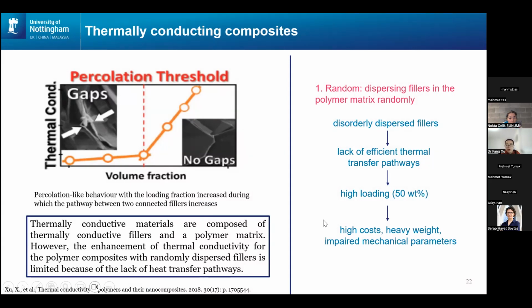So those disorderly dispersed fillers, or randomly dispersed fillers, don't have an efficient thermal transfer pathway. We can add more and more fillers in, and we can achieve good thermal conductivity if the loading is as high as 50 weight percent. But this is not what we want, because it means high cost, heavy weight, and impaired mechanical parameters. As you can imagine, when the loading of filler is very high, the mechanical property will drop.